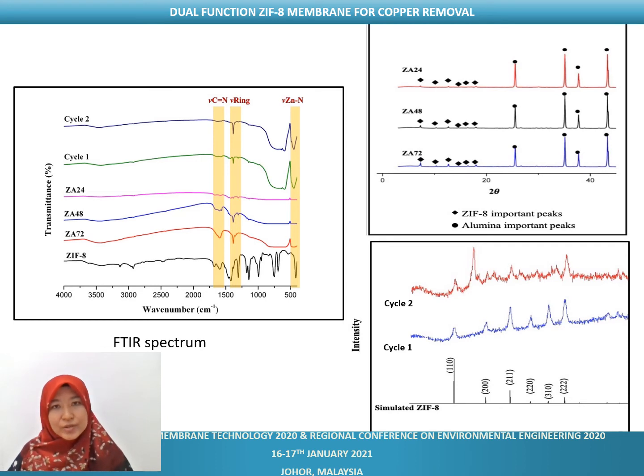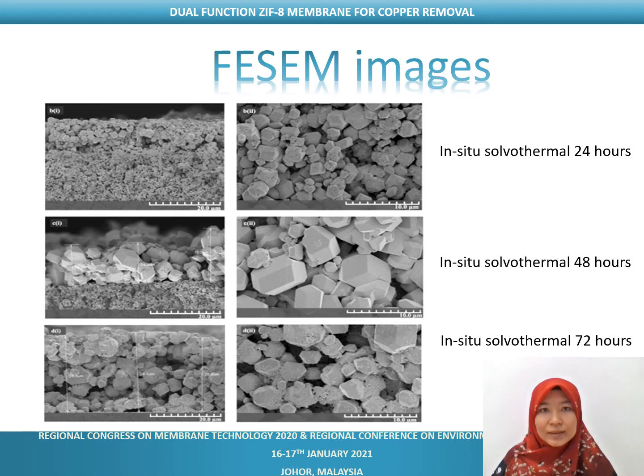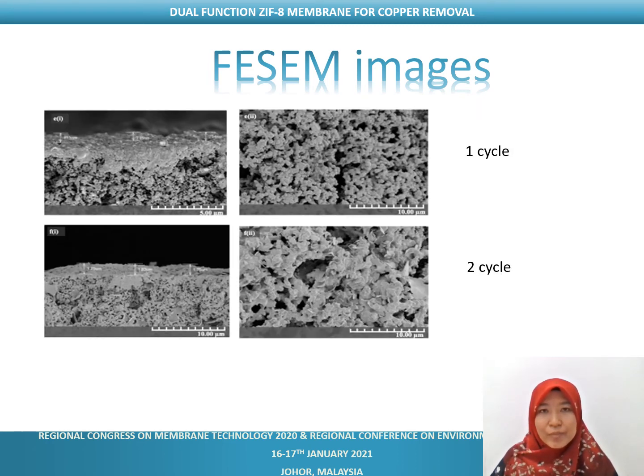For the FTIR spectrum, the membranes have all the important peaks attributed to the existence of ZIF-8 as mentioned earlier. It is noted that increasing the duration of reaction also contributed to the morphology of the crystal form. Increasing the time caused an increase in the membrane thickness, apart from the crystal size of the ZIF-8. Whereas for membranes prepared via the layer-by-layer technique, the ZIF-8 layer has no obvious crystallite structures, as can be seen in the FESEM images of the in situ solvothermal method. The layer is also thinner compared to the solvothermal method's membranes.